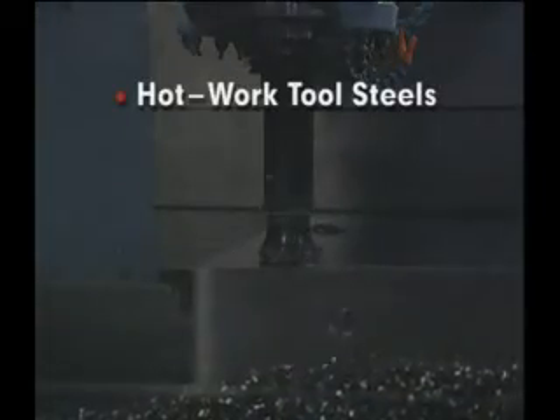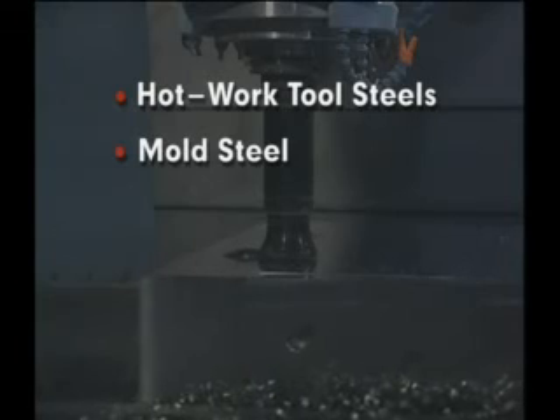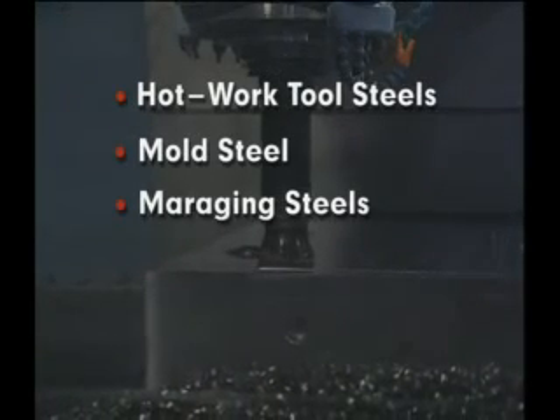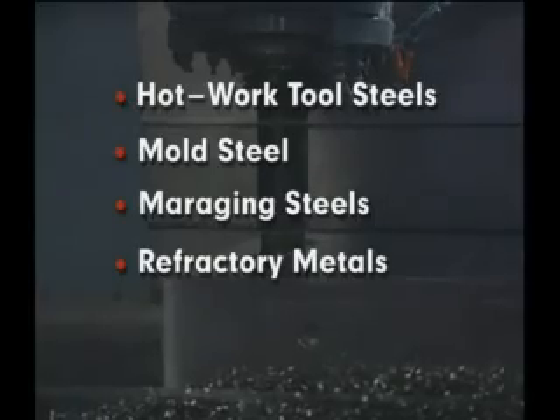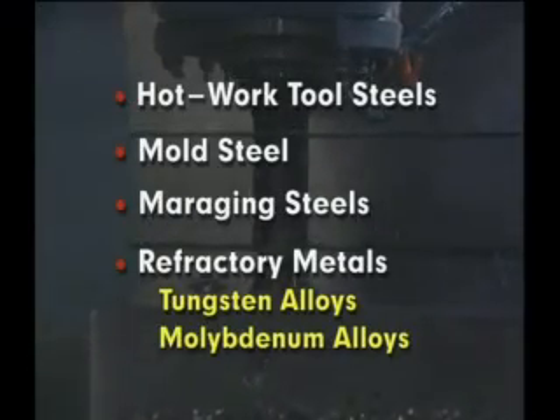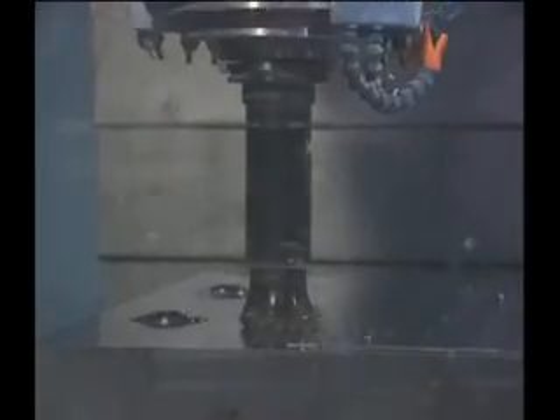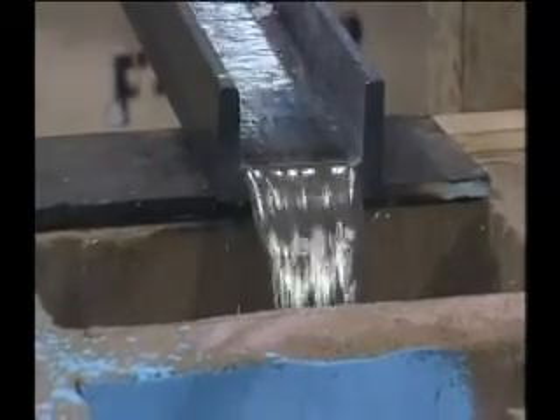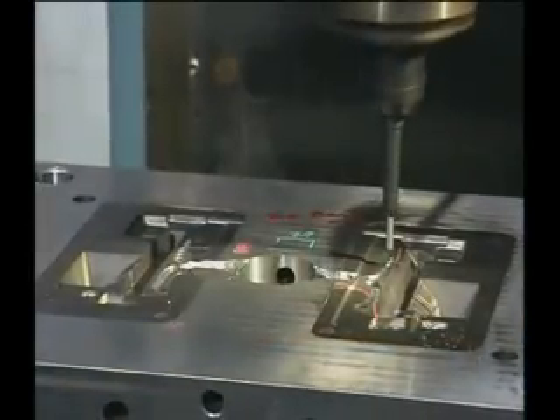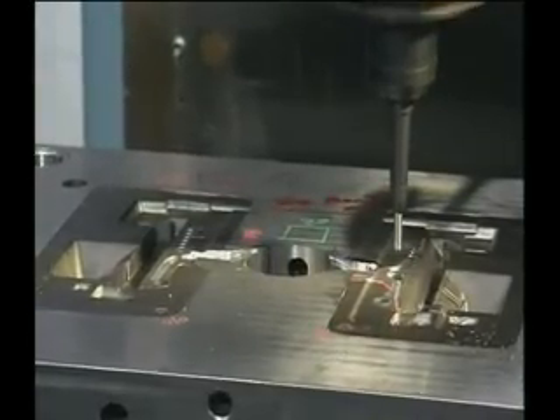Dies are usually produced from hot work tool steels, mold steel, mar-aging steels, and to a lesser extent, refractory metals such as tungsten and molybdenum alloys. All tooling materials are noted for high hot strength and high temperature wear resistance. Dies are usually made by machining from blocks of wrought metal, but they also can be cast and machined. Because of their machined features, precision, and materials used, die casting tooling is expensive, but the dies are reusable for thousands or even hundreds of thousands of parts.